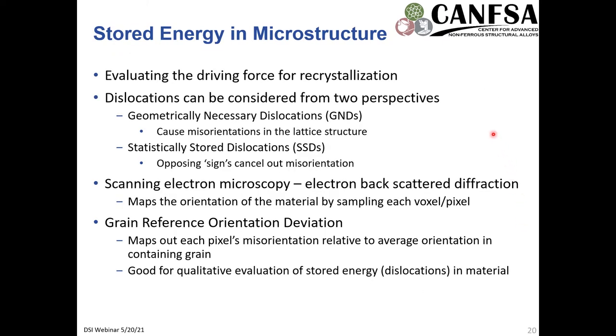And so, stored energy within the microstructure. We're going to go through and describe the evaluation technique we utilized for this. This is stored energy in the form of dislocations, and we're evaluating this as a driving force for recrystallization. And these dislocations can really be considered from two perspectives: geometrically necessary dislocations, as well as statistically stored dislocations. The geometrically necessary dislocations cause misorientations in the lattice structure within the grain, and statistically stored dislocations are of opposite sign, and they cancel each other out. Typically, for characterization techniques, GNDs can be evaluated utilizing electron backscatter diffraction, and SSDs can be evaluated using XRD.